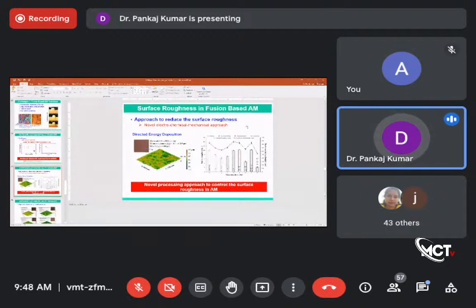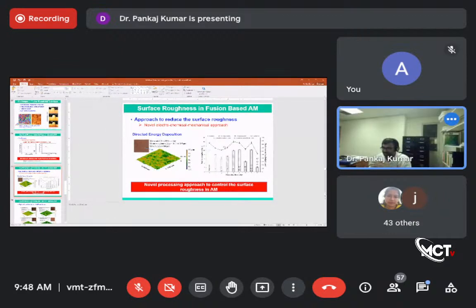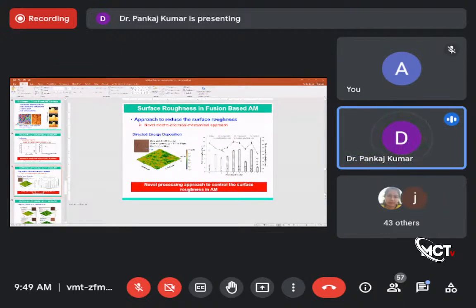So there is the post-process technique that we have developed recently. We cannot do this during the additive manufacturing process; you really need to do post-processing. That's why you have the hybrid manufacturing technique, where you simultaneously make and remove some material. You can also use a post-processing method to remove the surface roughness. Using different techniques, the surface roughness was reduced from about 10 microns to less than a micron. That is a very significant improvement, okay?